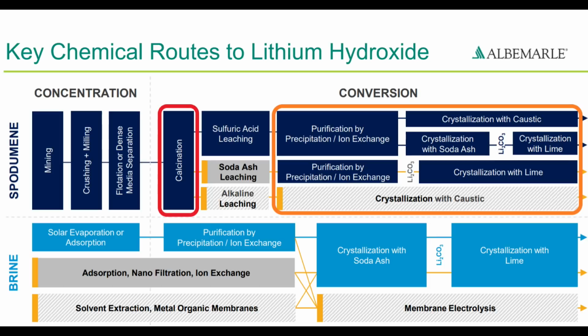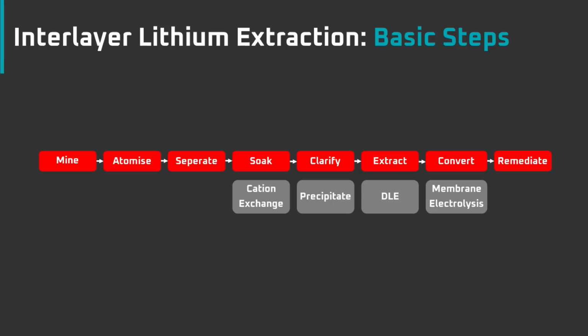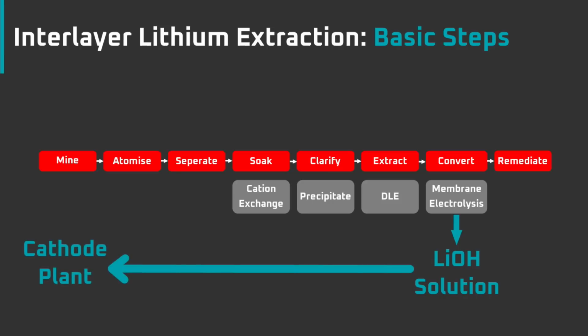Second, once at the hydroxide plant, it takes large amounts of heat and chemicals to convert the lithium concentrate to lithium hydroxide. With the clay interlayer process I just described, everything would be done on-site with a fully vertically integrated process that doesn't require heavy transport, energy usage for heat, or chemicals. Furthermore, if the output is lithium hydroxide as a liquid, they could also build a cathode plant on-site and pump the lithium hydroxide solution next door. This would save the chemicals and/or heat normally required to turn the lithium hydroxide liquid into a powder.